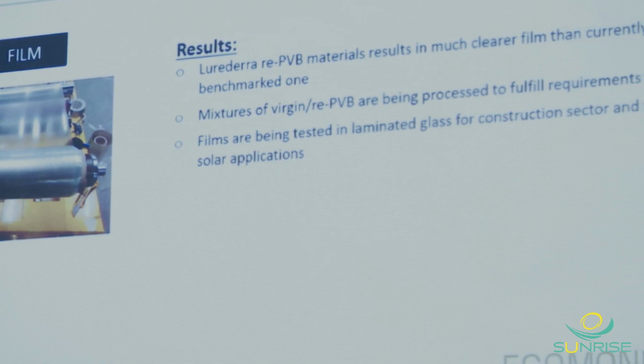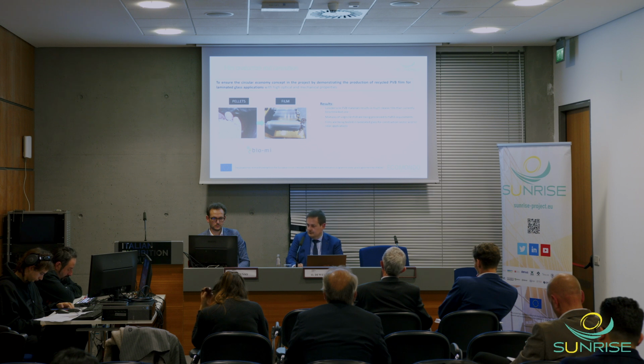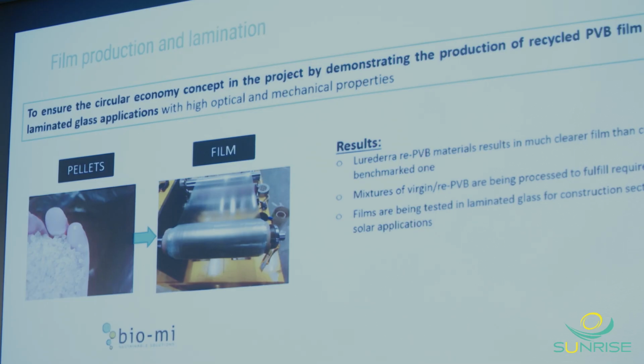But this was not enough. When we go to process a new film for laminated glass applications, even though we have better results than current ones in the market, we need to mix with virgin PVB in order to reduce aspects related with haze and yellowness. So in the project, we have been working on mixtures of virgin and recycled PVB, and we have been able to produce these films.